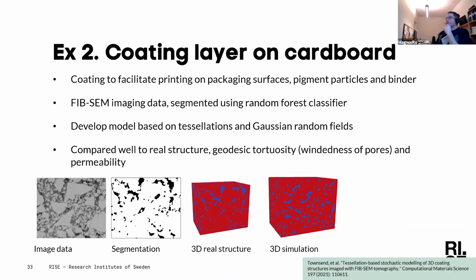Another example is a coating layer that Tetra Pak uses on a cardboard that they have for their packagings. They produce a lot of packaging materials. This is to facilitate inkjet printing on the surface. And in order to characterize this and understand its properties, we use this FIB-SEM electron microscopy method I talked about before. And we used the random forest classifier method that I explained before. We developed a virtual model for the structure. And comparing the real structure to the 3D simulation, we got very similar results in terms of these mass transport properties, the permeability and so on.